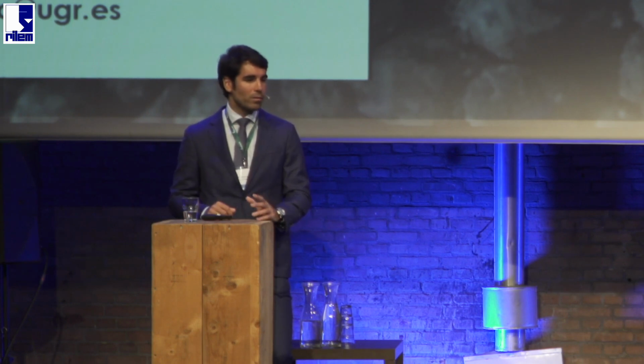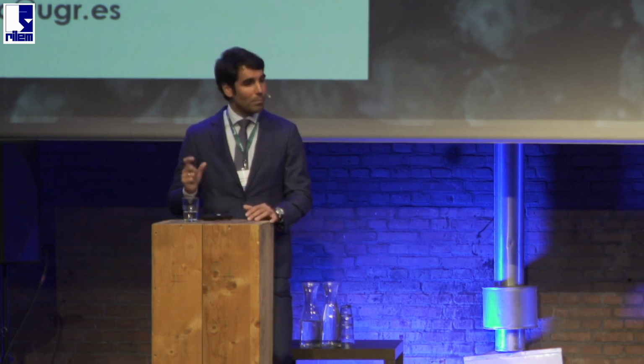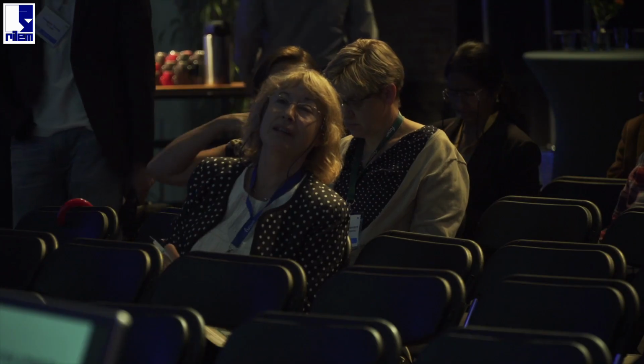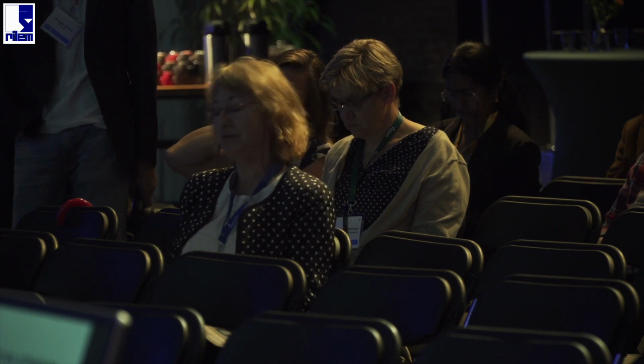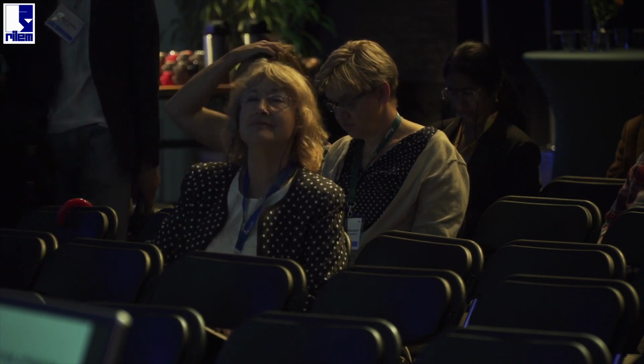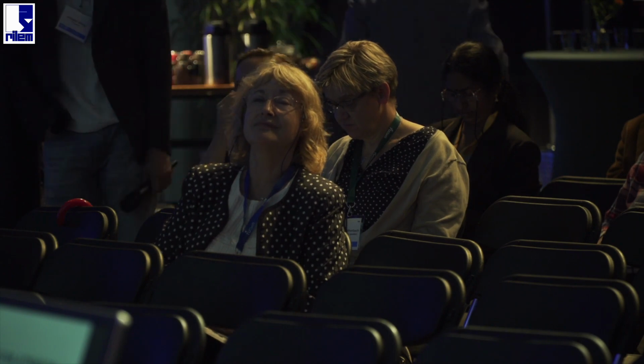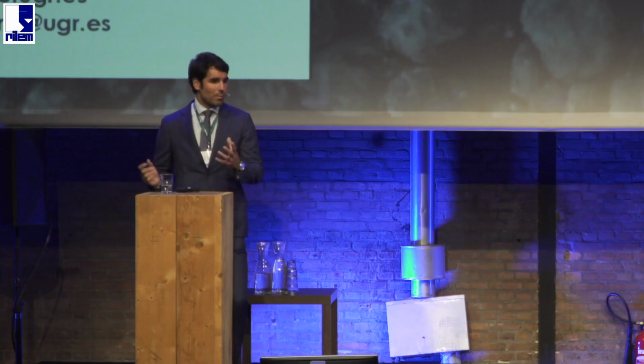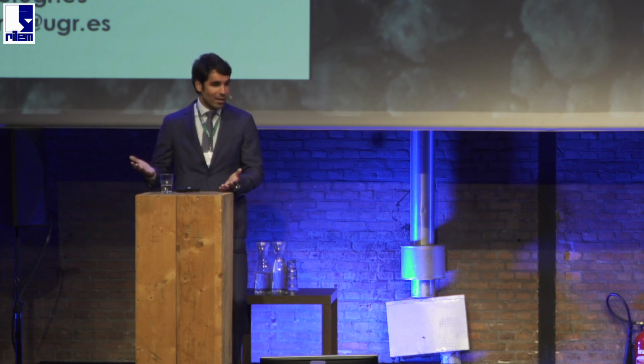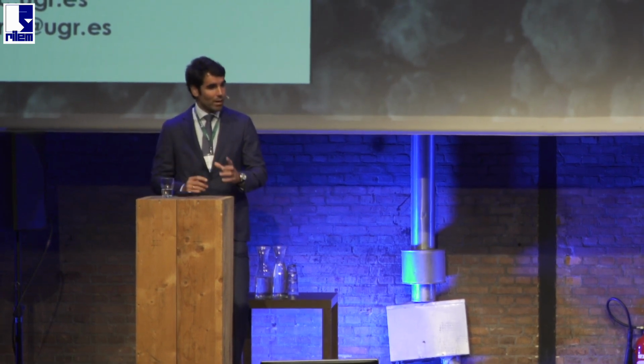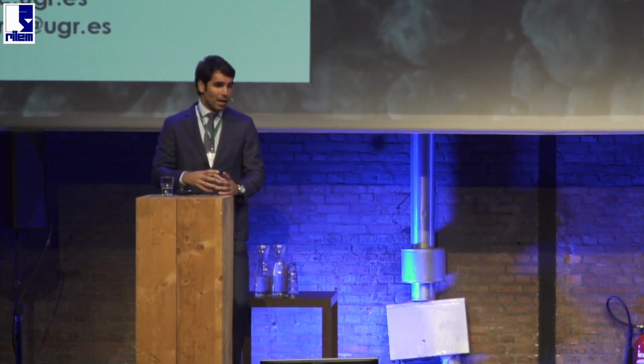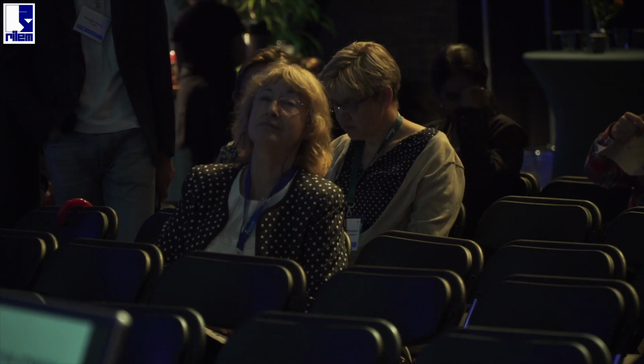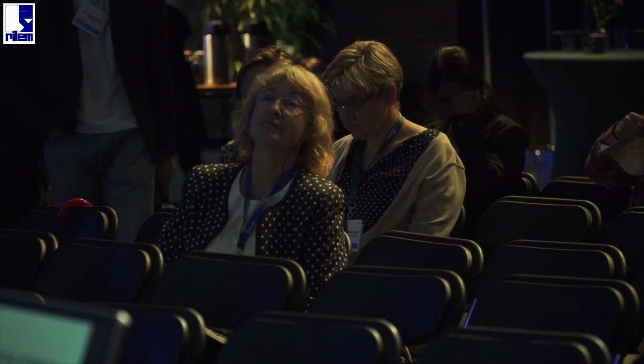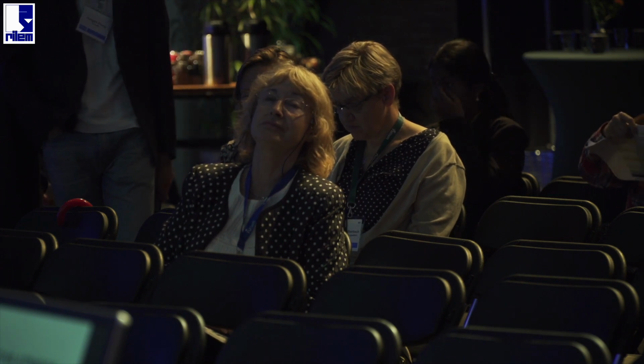Normally rheology is used for asphalt binders. Here, we are studying asphalt mixture, the complete mixture. So, for sure, rheology is a very interesting tool, but we are not far away from it, because rheology is the study of how loads affect the strain with time. We are doing all that, because we are controlling dissipated energy and the deformation produced in different load cycles. We take into account the number of load cycles, we have the frequency, so indeed we have time.